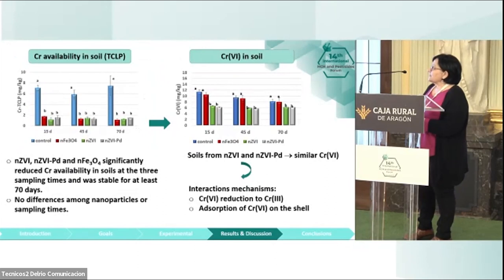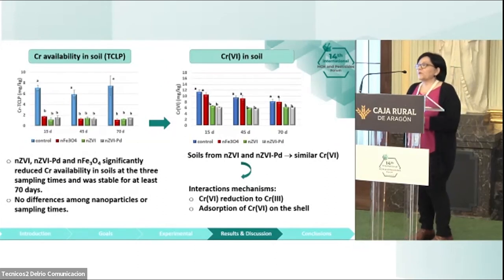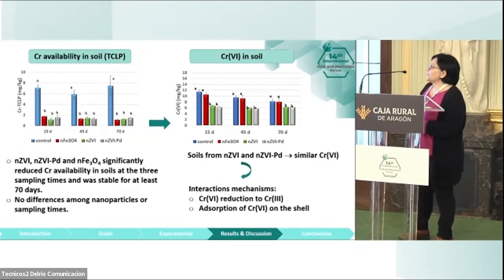We also conducted a test about Cr availability in soil. We used the TCLP, which has to do with lixiviation. What we can see here is that the three nanoparticles significantly reduced the chromium availability in soils at the three sampling times, and this was stable for at least 70 days. This was also fast, because after 15 days the concentration had been reduced and it was stable.